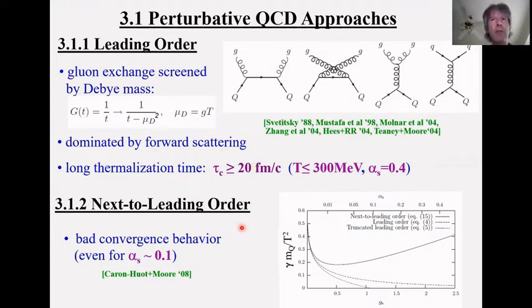Now, there's in a way more bad news for the perturbative approach here, in that the calculation of the next leading order to these scattering diagrams or to the transport coefficient really shows a very bad convergence behavior. Here you have a quantity which is essentially that thermalization rate, and you see when you start from the leading order result, which is this dashed line here, and calculate the next leading order correction, even for a coupling constant as low as, let's say, 0.1, there's a very large correction, let alone if you go to more realistic coupling constants where the correction can be a factor 10 or more. So really, even without invoking any non-perturbative effects, the convergence is very bad, and you cannot really get any reliable estimates for what we think are realistic coupling constants.